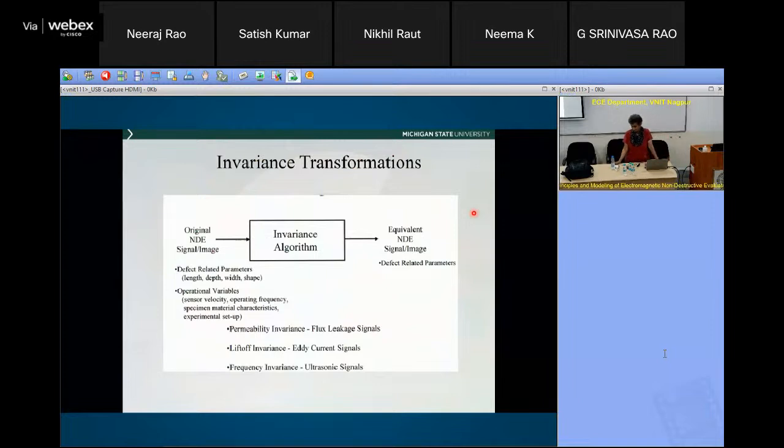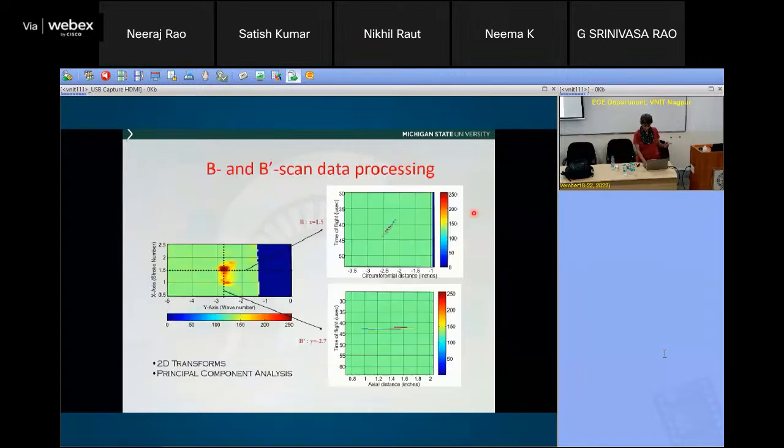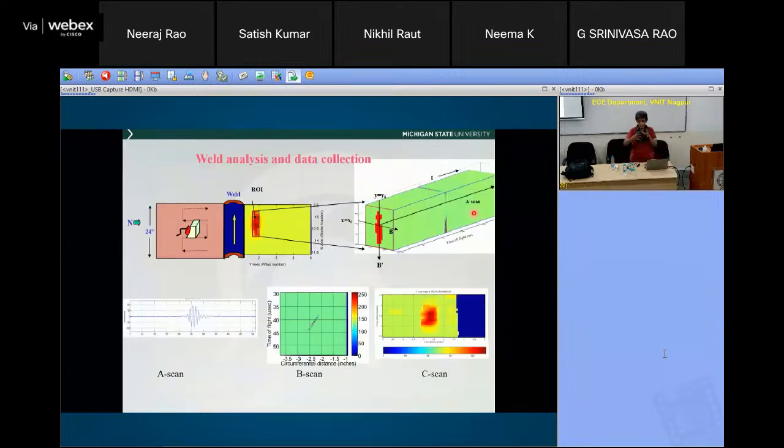Data was collected by transmission, and that was fed to some reprocessing. After that, we got these images. As I showed over here, in ultrasound you are generating a three-dimensional volume. You have a raster scan, X and Y, and at each point you have time data. So you really have a lot of data. Even though what I showed is just the C-scan image, we are looking at a lot of data, and it's a holistic analysis of all that to come up with classification.